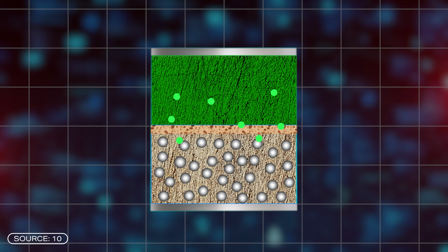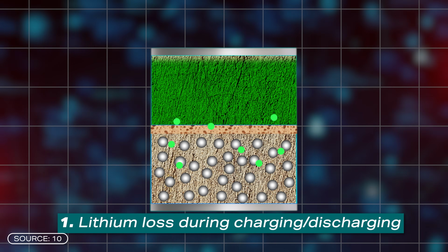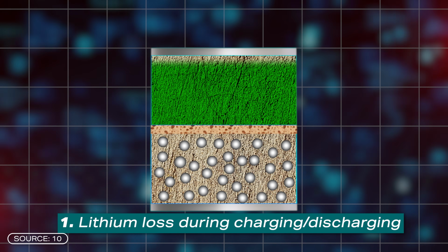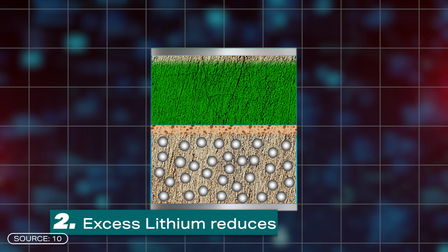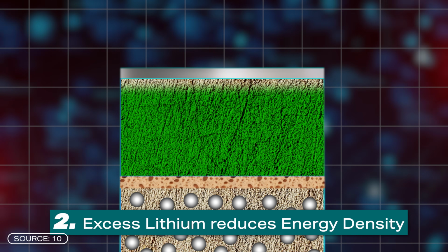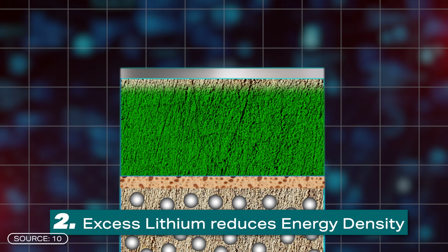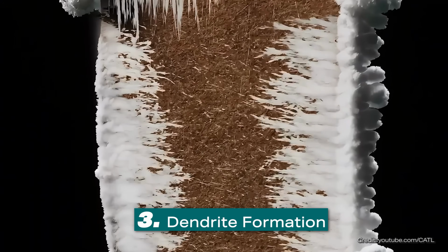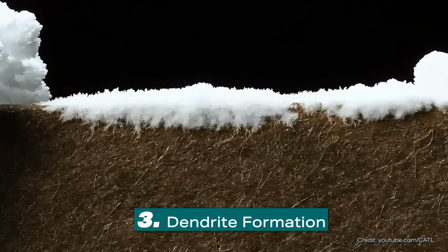This creates three problems. First, lithium is constantly lost during charging and discharging. The excess lithium can compensate for the losses. That sounds pretty good at first, but it means the measured efficiency is higher than the actual efficiency and you don't immediately notice the lithium loss. The second problem, the excess lithium is of course expensive and takes up space, which in turn reduces the energy density. And then, of course, there's still the problem of dendrite formation when there's too much lithium in the system, but we'll come back to that later.